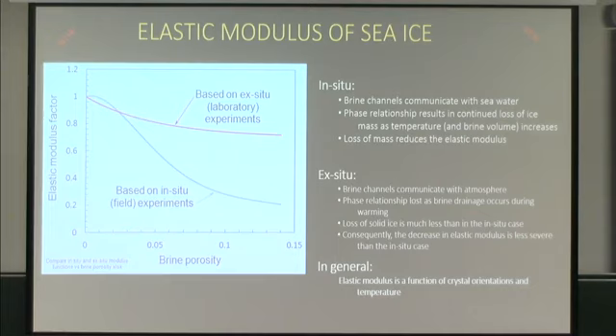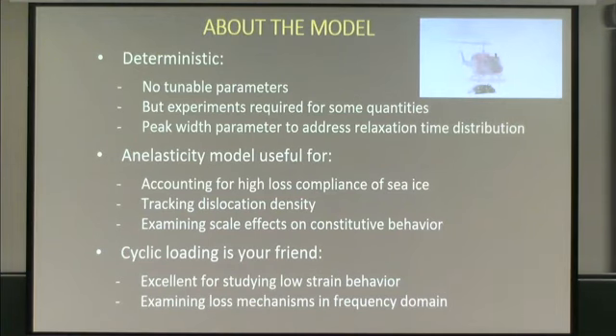Out in the field, what happens is you have floating ice. The brine inclusions open up when it warms up, but they're in a column of water. So the ice stays in contact with brine, which keeps eroding away the pure ice part of the matrix, to the point of giving you about 25% of the elastic modulus because of that loss of ice mass in the structure. The next iteration of the model, which I'm going to be working on after this meeting, will capture that. But if you do any kind of modeling, looking at lab results and trying to extrapolate to the field, you have to be very cognizant of features such as this.